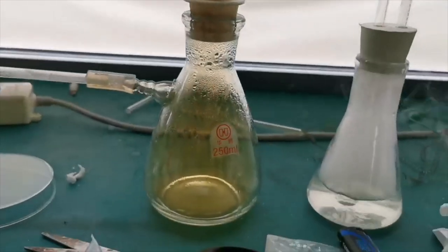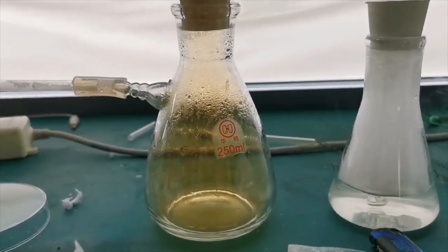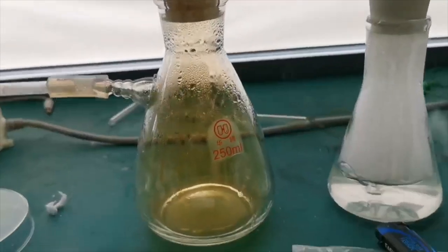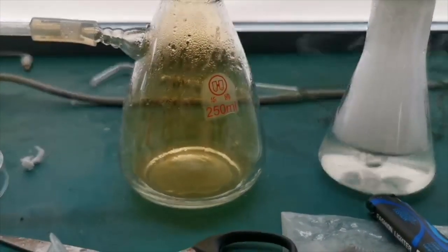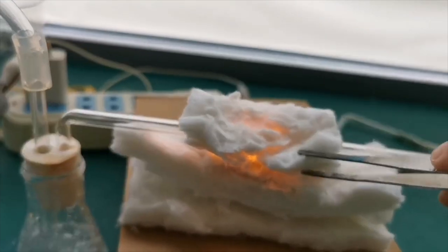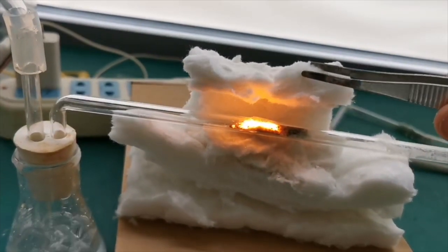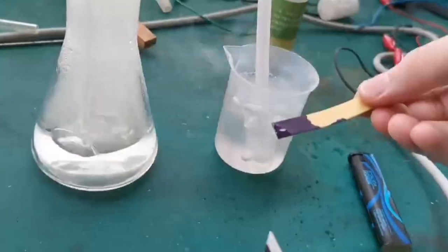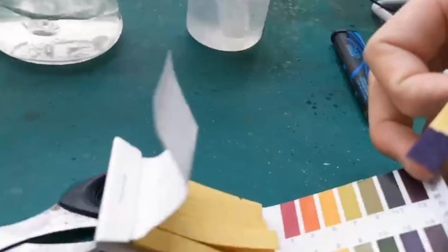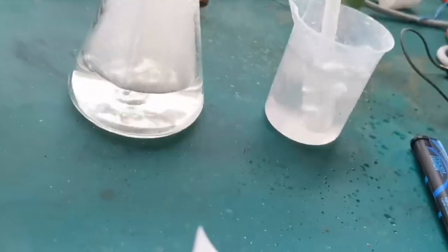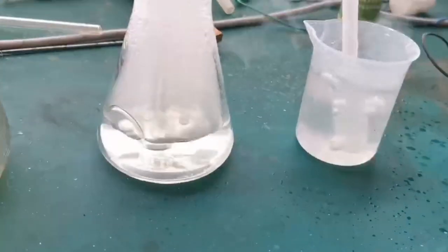During the first stage, the reaction didn't start at all, and the flask, being filled with ammonia, stays clear and colorless. When the catalytic reaction starts, the catalyst glows, and white fumes of ammonium nitrate appear in the flask. Finally, the third stage, which is the stable production stage, begins when the fumes all disappear, and the gas turns entirely brown. The first and third stage may be confusing to distinguish, especially when the nitrogen dioxide concentration is too low and the brown color isn't obvious. However, keep in mind that as long as the catalyst glows, the reaction must be going, and when the catalyst stops glowing, the ammonia is nearly depleted, and it is now time to change the ammonia solution to a more concentrated one.